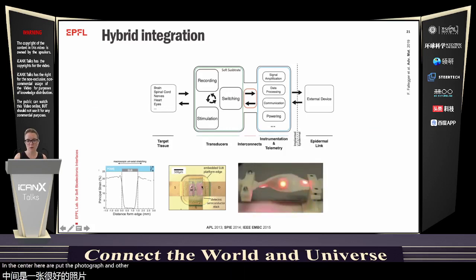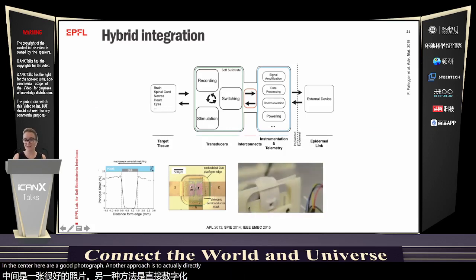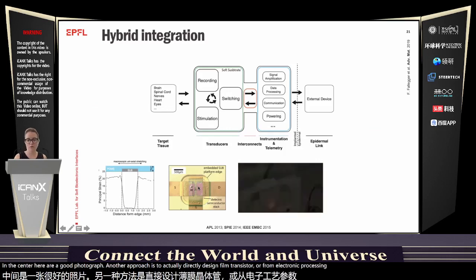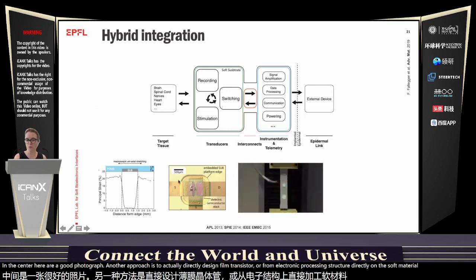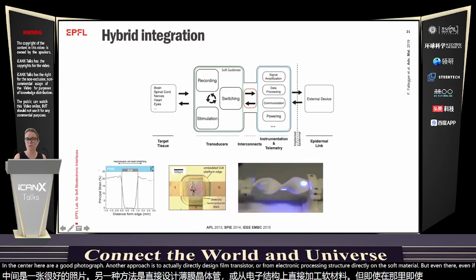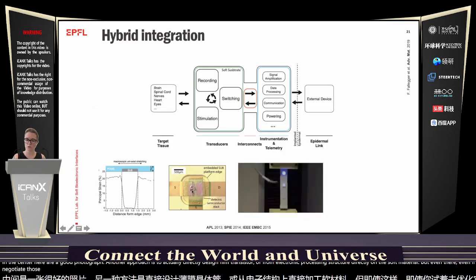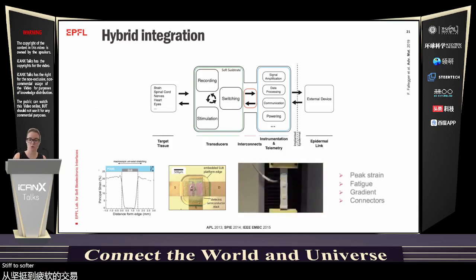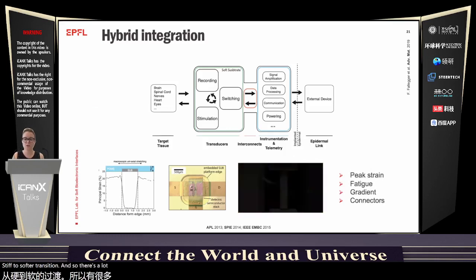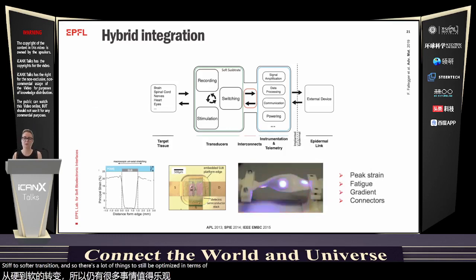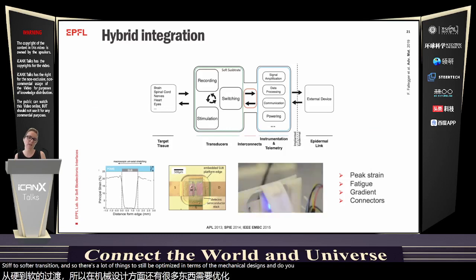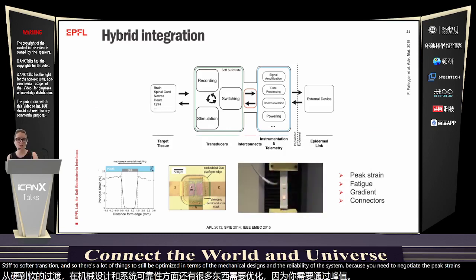Another approach is to directly design thin film transistor or film electronic processing structures directly on the soft material. But even there, even if you try to optimize the materials, you also need to negotiate those sharp, stiff to soft transitions. And so there are a lot of things still to be optimized in terms of the mechanical design and the reliability of the system, because you need to negotiate the peak strains. You also need to ensure that the overall system doesn't fatigue.